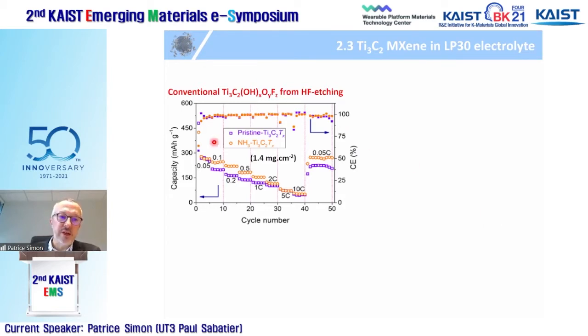This is the change of the capacity versus the cycle number at different C rates, different rates of charge and discharge, for a conventional HF MXene. And what you can see is that at a 10 C rate, which means a charge discharge within 6 minutes, you are at less than about 50 milliampere hour per gram.